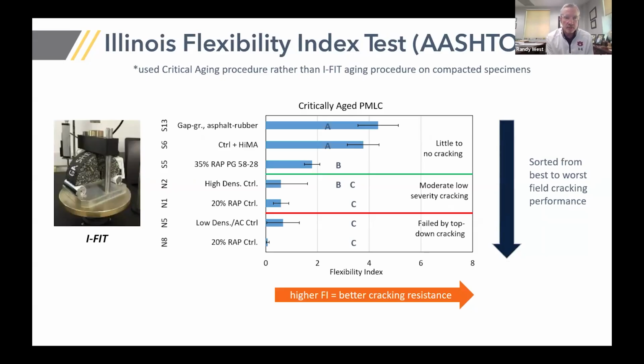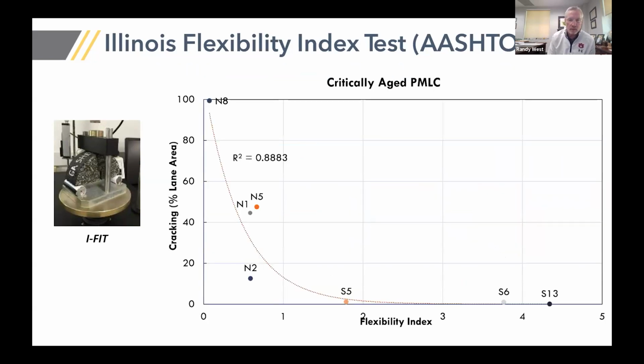Another test that is used and has been very popular over the last couple of years is the Illinois Flexibility Index test, or IFIT. It is used in the state of Illinois. And you see it rank the mixes very well in terms of the ranking versus the field performance that we observed. And the correlation, the R squared for this test, is 0.89. So that's really a really strong correlation.